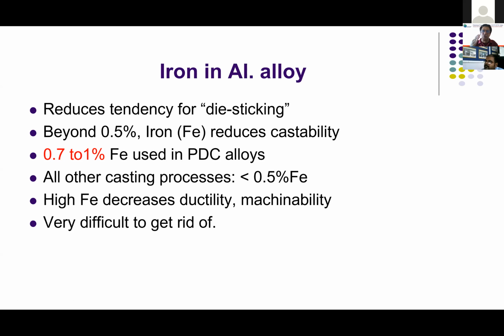Especially for gravity and low pressure, where the metal is held for more than 6 hours, 8 hours inside the crucible. There, the problem is iron pickup will be more. If you measure the iron at the beginning of the shift and the end of the shift, you will see that there is a marginal increase in iron. Iron once it gets into the molten metal, it is difficult to remove it. Reduction is impossible. Removal is impossible. Reduction is possible only by dilution.